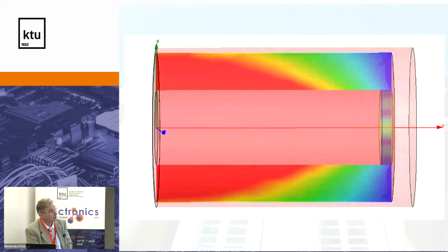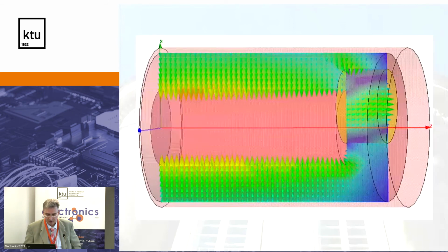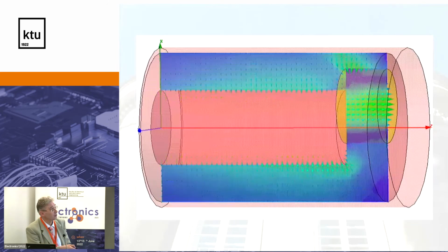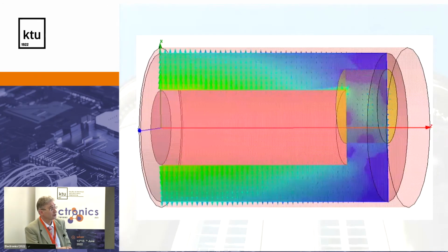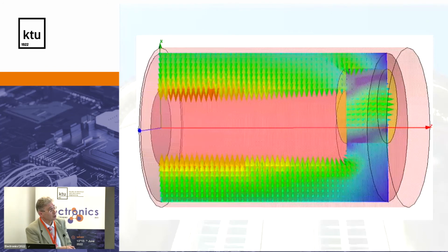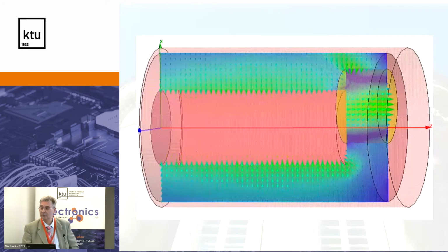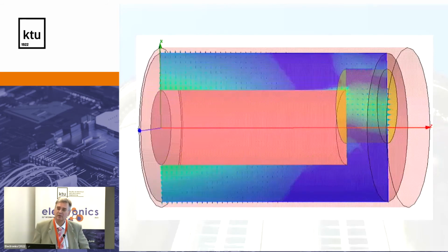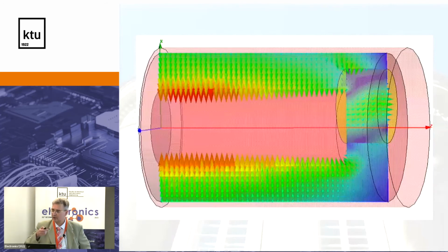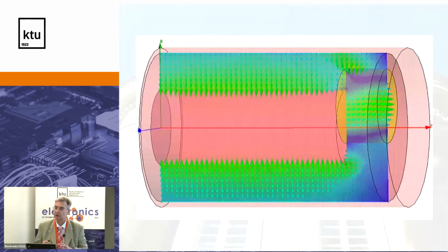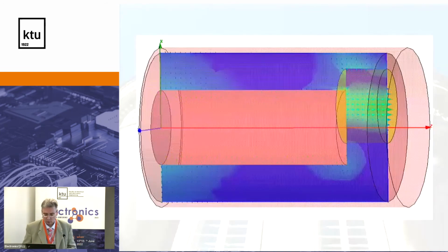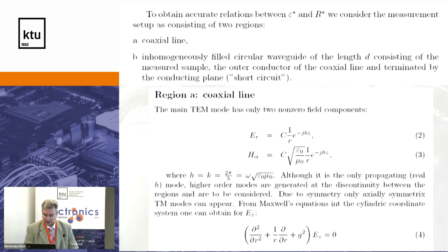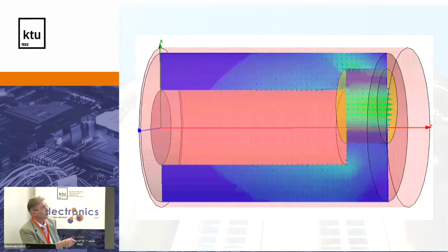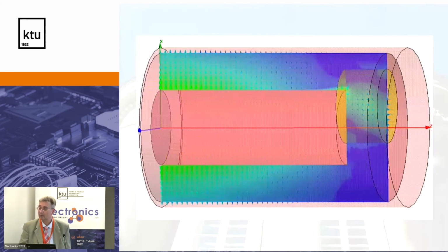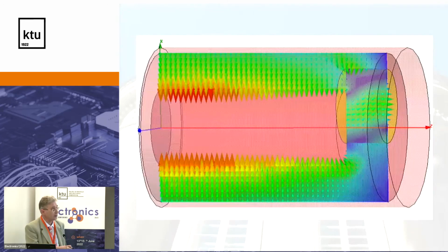Here again, another example, maybe better to see how the electric field is distributed inside the sample. And even if you place a sample a bit not straight on the axis line, you can see that some rotating modes appear in this sample. So even the dynamic capacitor model with Bessel functions, which I showed, rather complicated, is not efficient, not working very well. So what to do? The idea is to separate. This part is a coaxial line, usual mathematics, and at the end, we should use another.